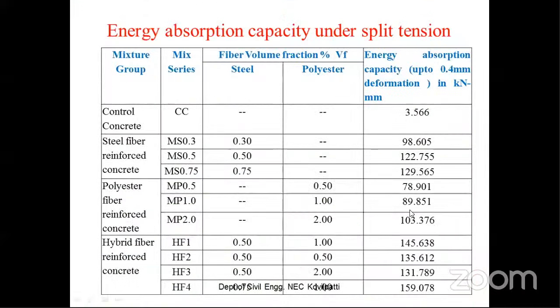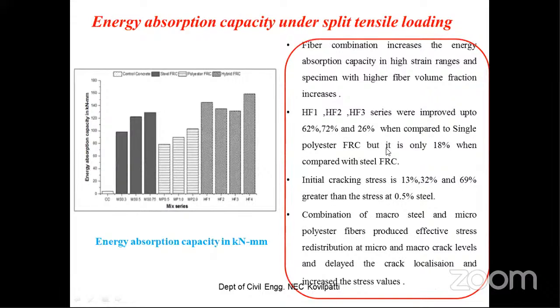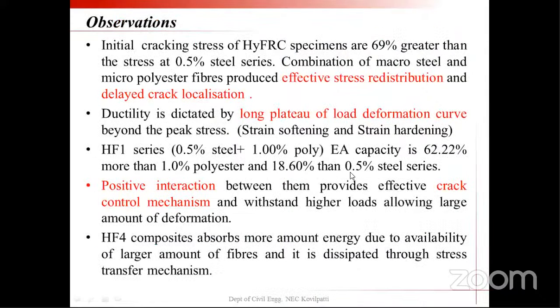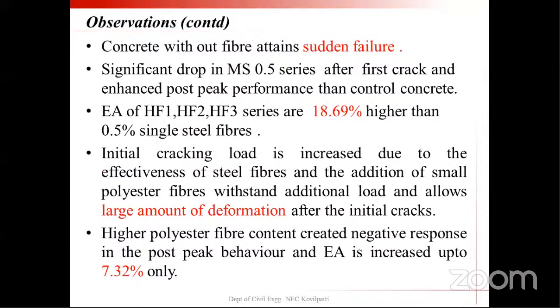And the energy absorption capacity values represented in the diagram are shown in the sketch. And this is a comparison made, and the initial cracking stress improvement has been observed to be in the range of 13 to 69%. And in the HF1, 2, 3 series, the values have improved by 62, 72 and 26%. So all these observations were made in the experimental part. I can see the initial cracking stress improved by 69%. It is because of the effective stress redistribution. And we can see the energy absorption curve, the deformation curve, is a long plateau. And I observed a positive interaction between the fibers because they provided an effective crack control mechanism to withstand the load. So some important observations were made.